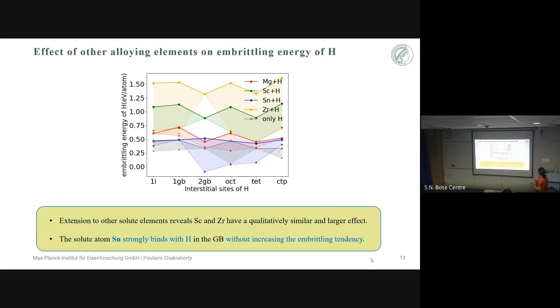And this is also definitely because the tin is strongly binding with hydrogen, and it is becoming a trapping site for hydrogen. But also in the grain boundary, it is not increasing the embrittling tendency. The zirconium and the scandium are also strongly binding to hydrogen, but they are increasing the brittle tendency. So you were asking about the chemical effect here. This is the difference in the chemical effect.